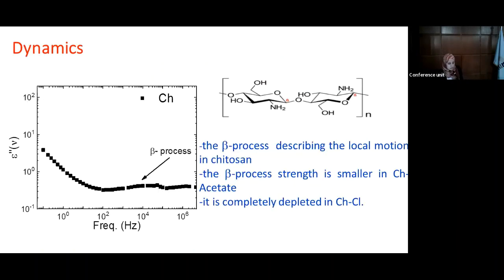For dynamics, we applied dielectric spectroscopy to see the molecular dipolar relaxation. And for chitosan, like any polysaccharide, we see such a process. We call it the beta process, and it shows some kind of local motions inside the repeating units. What about the derivatives?